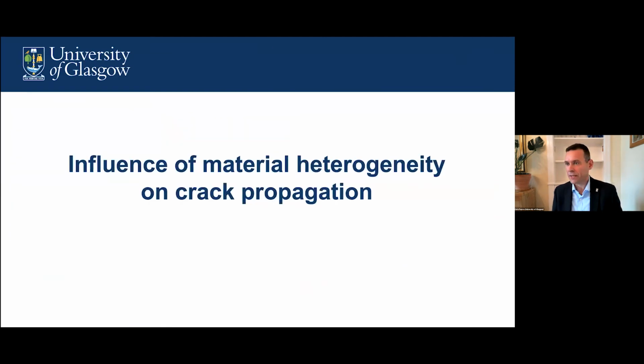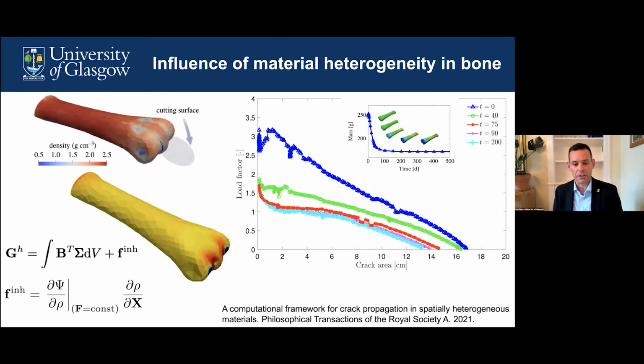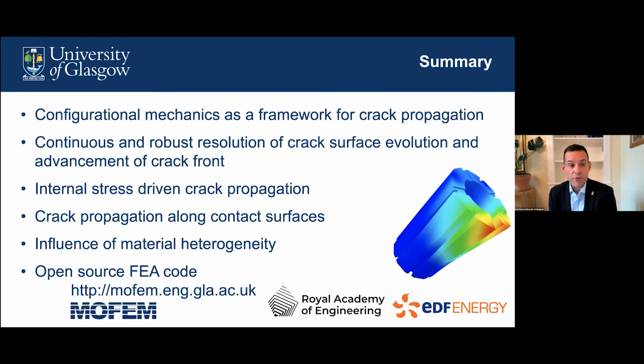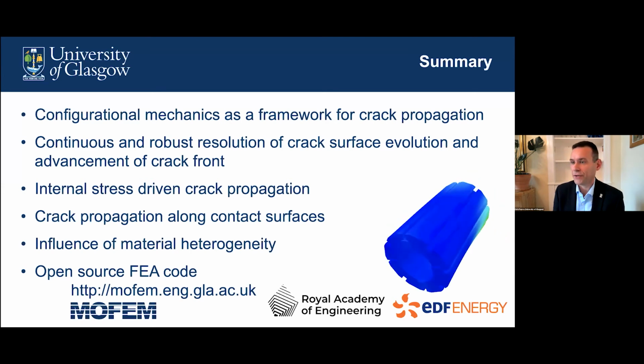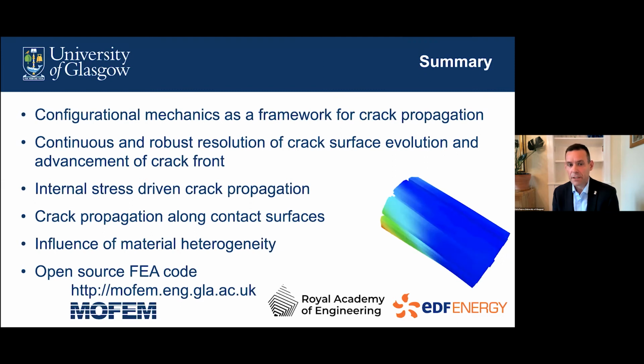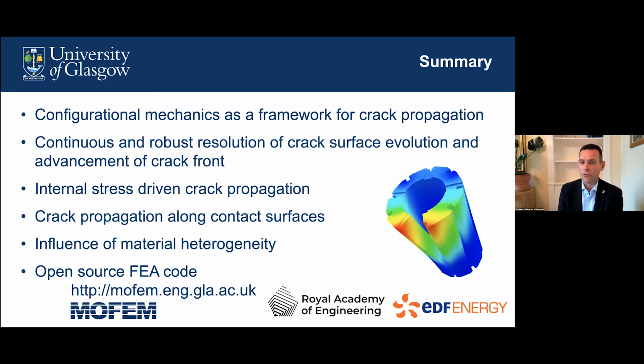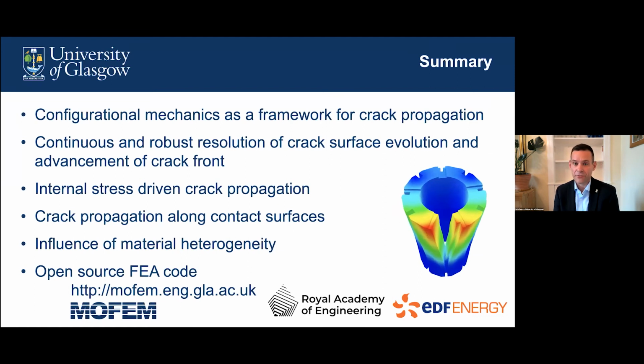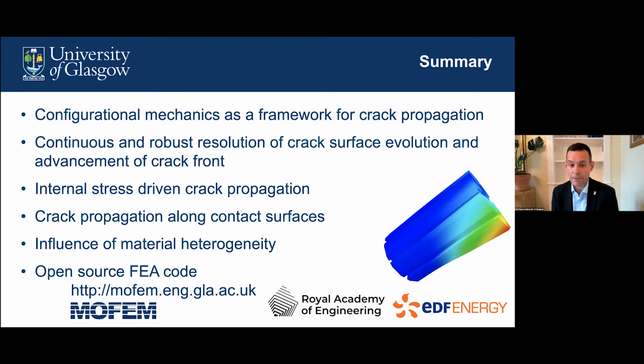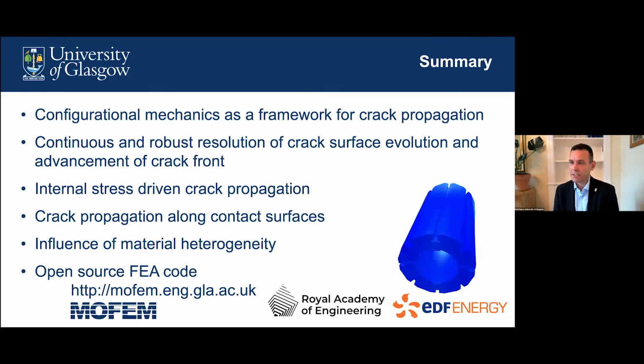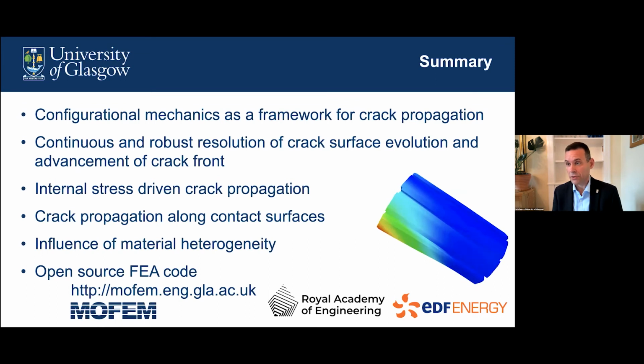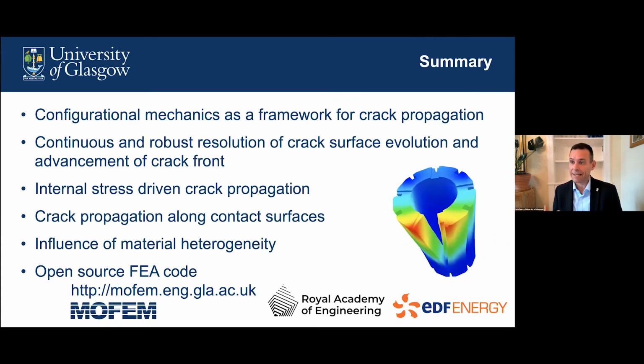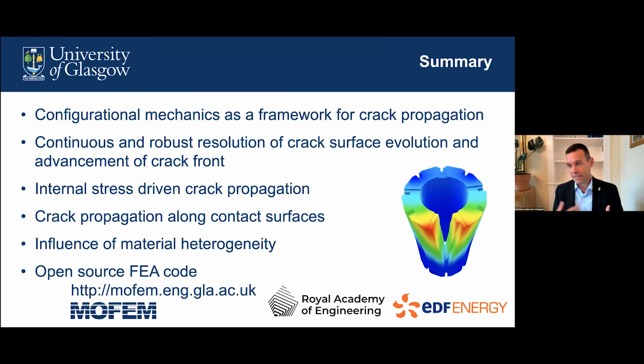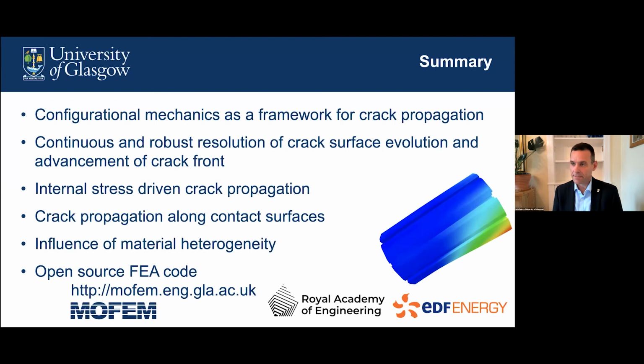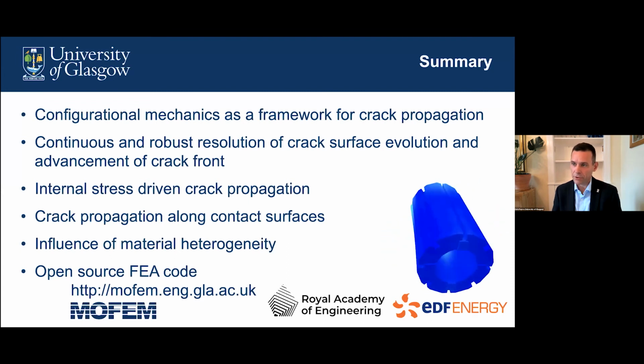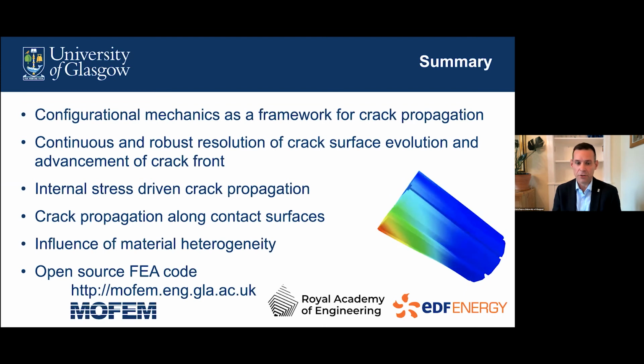Okay, I was going to show you very briefly material heterogeneity, but I'll skip it in the interests of time. So, in summary, we've used configurational mechanics as a framework for crack propagation. We have continuous and robust resolution of the crack surface evolution and advancement of the crack front, resolved within the context of the finite element method. The real challenge for us has been not to drive the crack through external loads, but to drive the crack propagation as a result of complex internal stresses. And the other big challenge we then faced is the interplay between contacting components and a propagating crack.